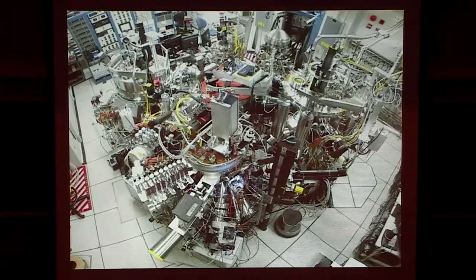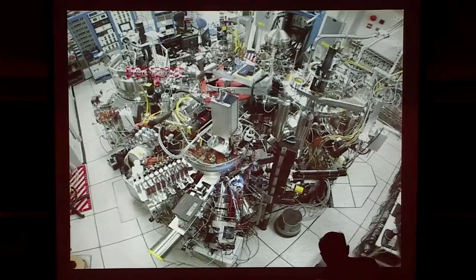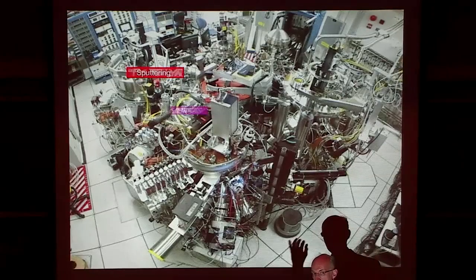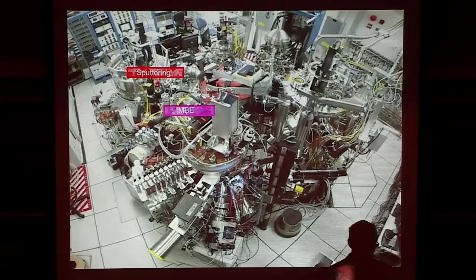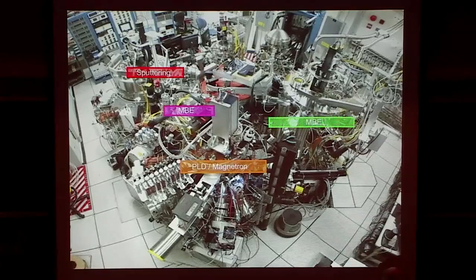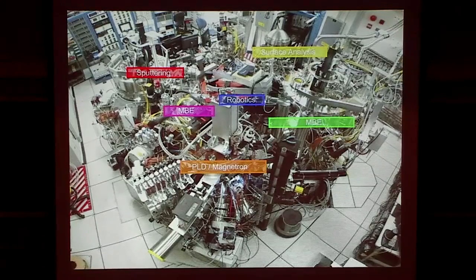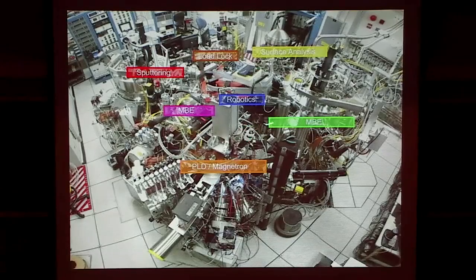Now, how do we make these materials, which, as I've emphasized several times, involve layers of different materials deposited one on top of each other, atomic layer by atomic layer? It turns out there are a variety of techniques, but this is a system that we built in my laboratory at IBM in San Jose. It's taken about 10 years, and it's cost about $10 million, and the size is about 40 feet by 40 feet. And can you see there's a central robotics chamber which is connected to a series of ultra-high vacuum chambers.